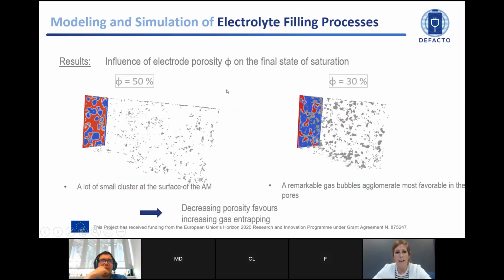And another outcome of the lattice-Boltzmann approach is that we can see the final state of the saturation, and here we can evaluate the gas entrapping. So depending on the porosity, there might be certain differences between the entrapping of the gas bubbles in the electrode. With the highest porosity, apparently there's certain gas bubbling on the surface of the active material, while in the lower porosity regime, we see that the gas bubble agglomerates are mainly in the pore structure.